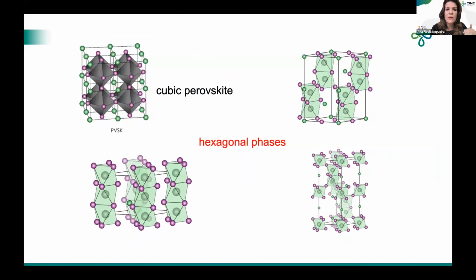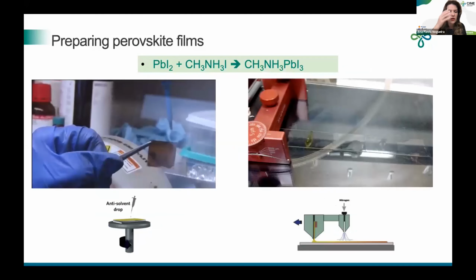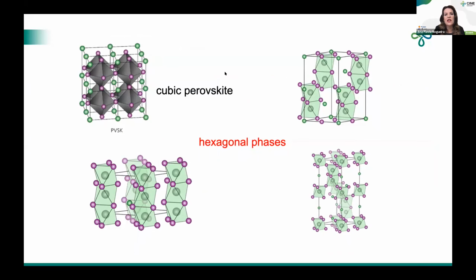So what we did was, just before talking about the data that we got in the synchrotron, it's important to mention that in all that process, what you want is the cubic perovskite, because this one is the one that is actually photoactive. But it's quite impossible to get rid of the hexagonal phases. Those hexagonal phases, as you can see here, are non-active for photovoltaics, because the octahedra are not linked in three dimensions. So we don't want this hexagonal phase, but it's really important to study them, because we are going to see that before forming the cubic perovskites, we pass through these hexagonal phases.